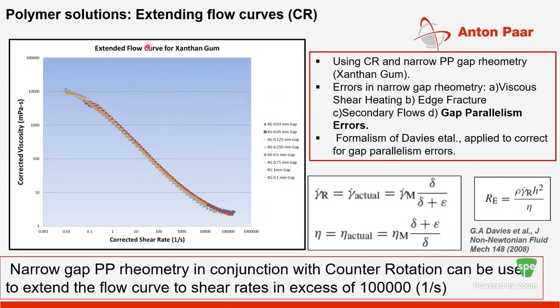One needs to be very careful while doing such measurements because you need to do narrow parallel plate rheometry type experiments, and you need to worry about all these artifacts which can come into the data, like viscous shear heating, edge fracture, secondary flows, etc. So you need to address them, and I did that.